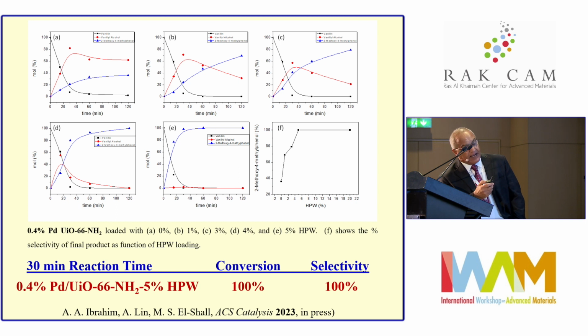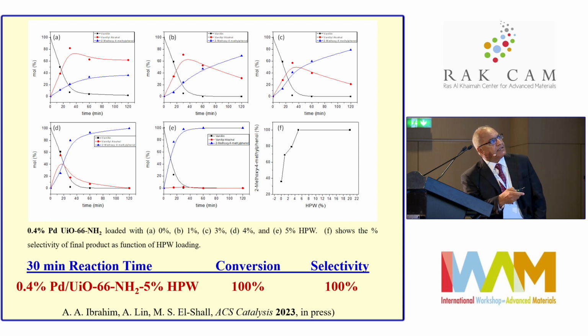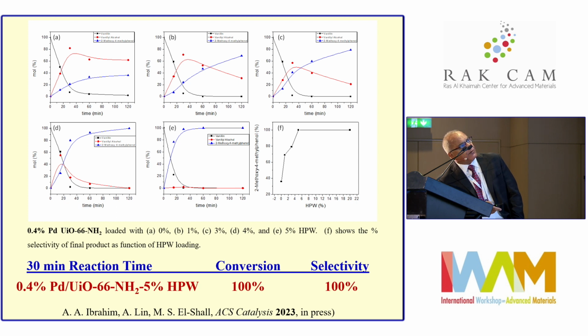We look now at the reaction profiles, the time profile for the reaction, and you can systematically see that the product starts to improve by increasing the amount of HPW loading. So this is the first one here with no HPW. You have vanillyl alcohol as the major product, and the methoxyphenol is in the middle here. But as you go to 1%, the methoxyphenol starts to increase, 2% increases further, and we have here 4%, but when we get to 5%, we have actually 100% conversion. So this is only 5% HPW, and we have 100% conversion, and this is the conversion, as you see, as a function of the loading of HPW.